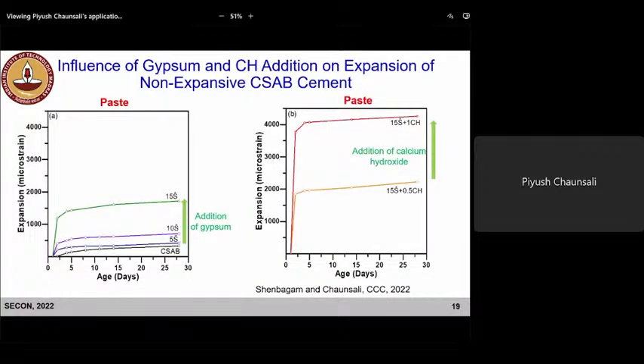So non-expansive cement can be converted to expansive cement. Non-expansive means the expansion is not significant, right? For non-expansive CSAB cement, through the addition of gypsum, 5%, 10%, 15%, a significant increase in the expansion can be achieved. So this is an example of paste here.